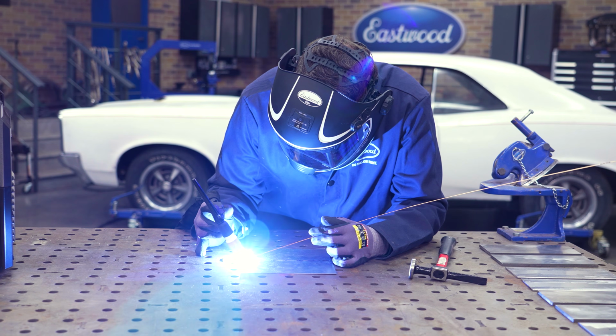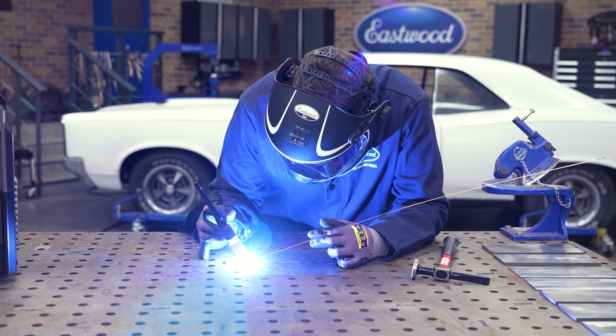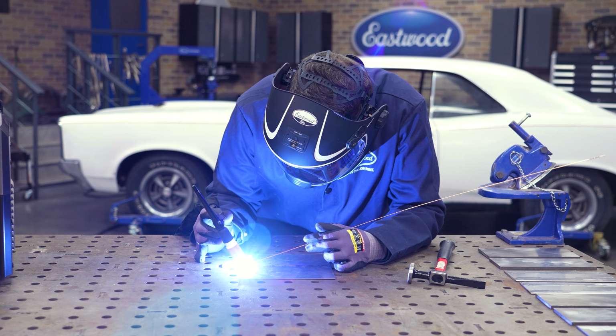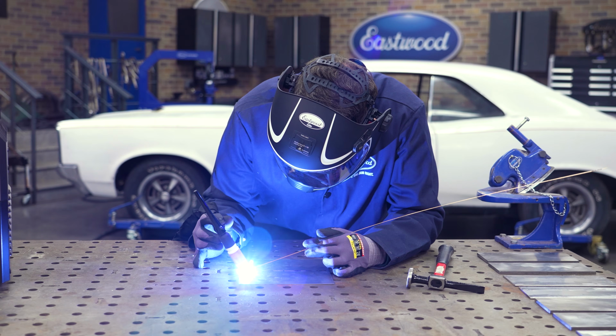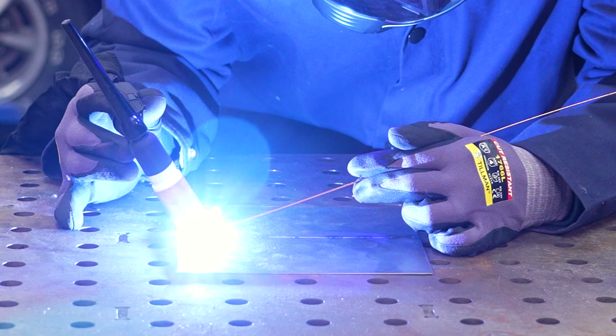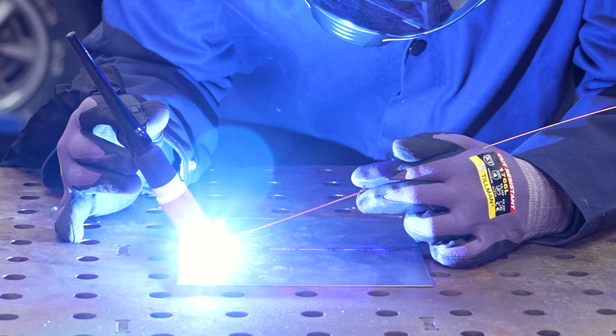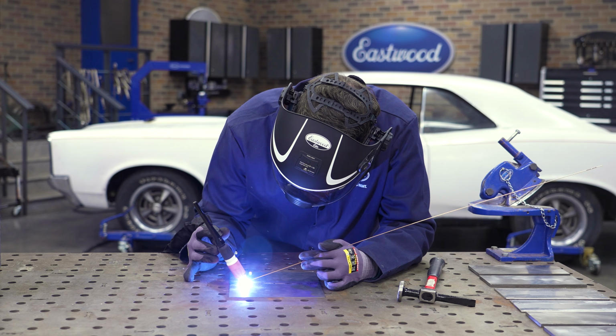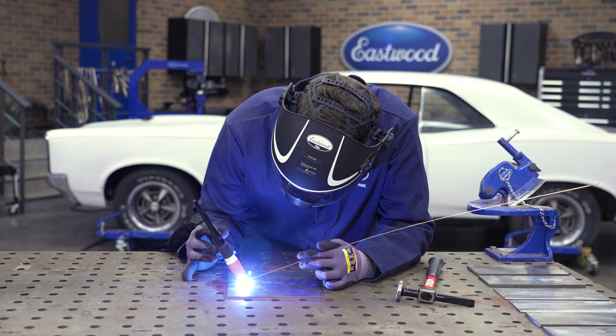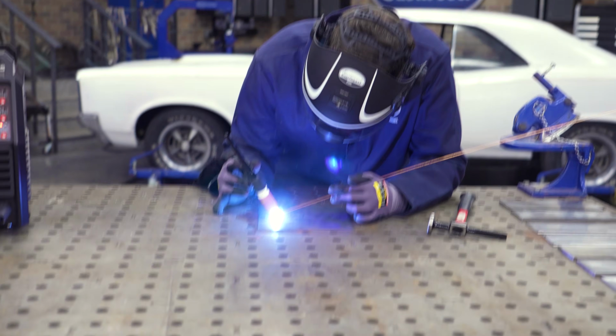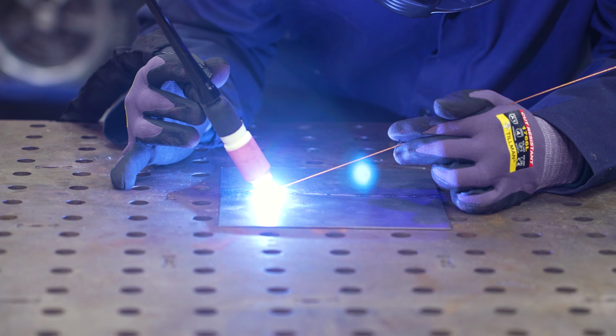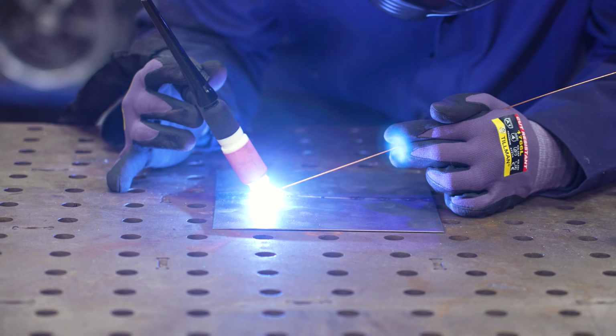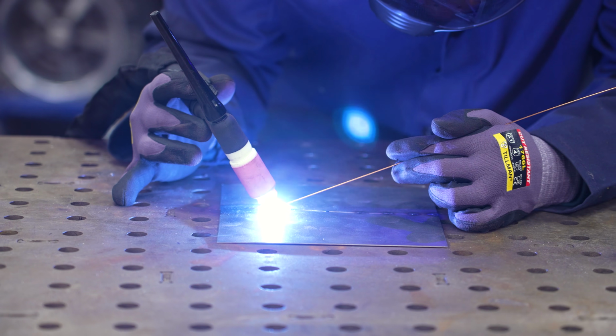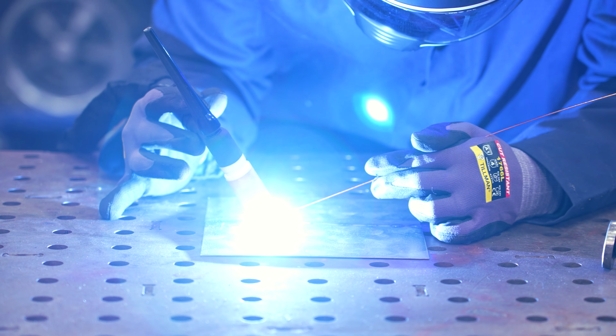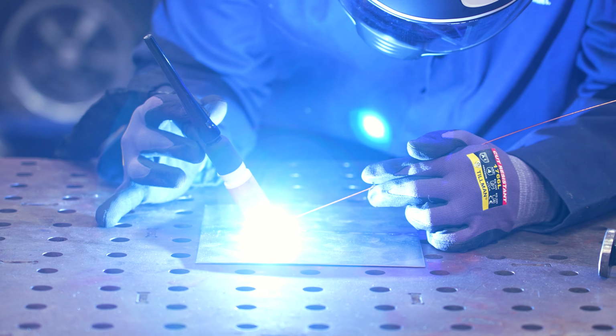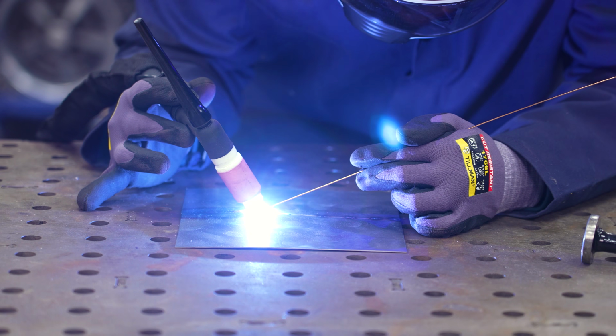So as I strike my arc here, you're going to see it pulse on and off, nice and slow. And the reason I say this is a little bit more beginner friendly is because when the pulse goes to the peak, I'm going to ram my filler rod in just a little bit, and then as it drops down, it's going to cool that puddle. And as it cools the puddle, I'm going to bring the torch to the front edge of the puddle. So that's going to help me identify my travel speed. That'll help me identify each dime as I'm welding.